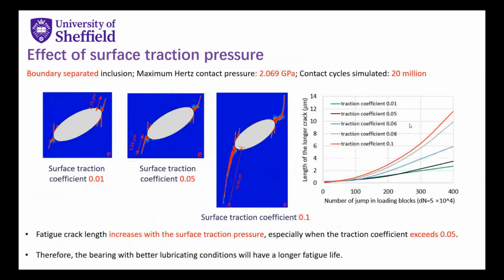Then I'm going to investigate the effect of surface traction pressure. I change this surface traction coefficient from 0.01 to 0.1 to see the difference between the surface traction pressures, and all other values are fixed, such as the maximum contact pressure and the contact cycle simulated. Based on the modeling results here, I think the fatigue crack length increases with the surface traction pressure, especially when the traction coefficient exceeds 0.05. That means when the lubricating conditions become worse, it will accelerate the fatigue and accelerate the damage of the bearing. So the bearing with better lubricating conditions will have a longer fatigue life.